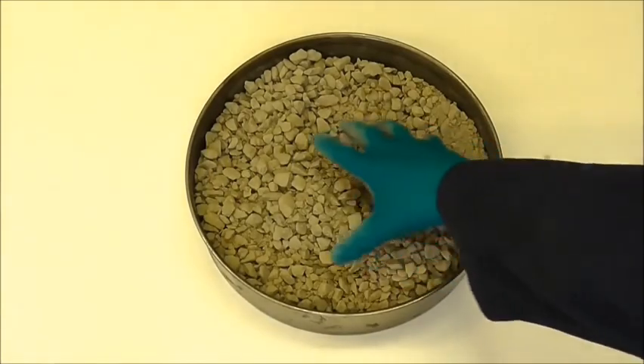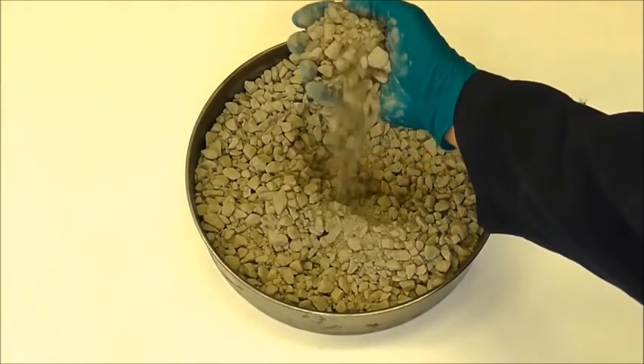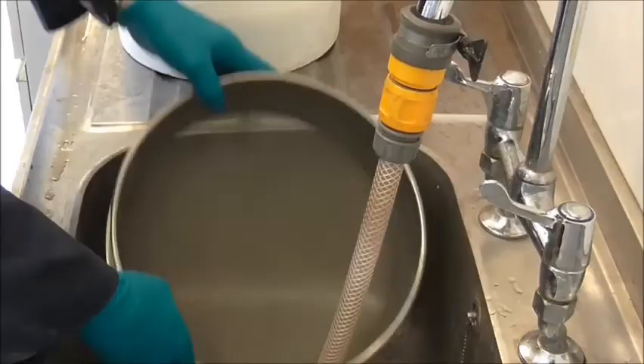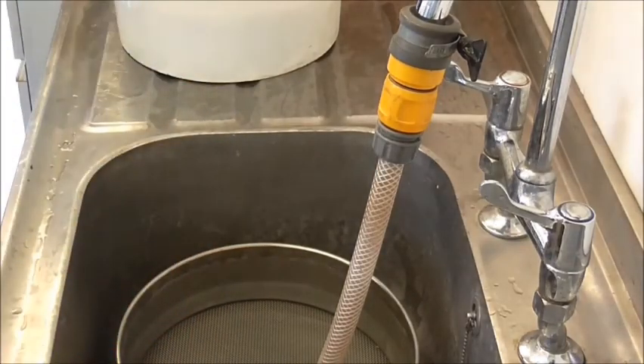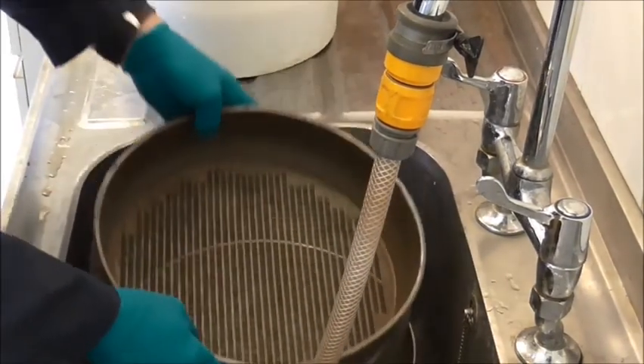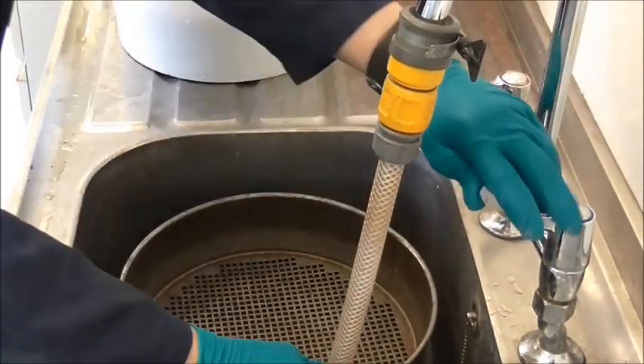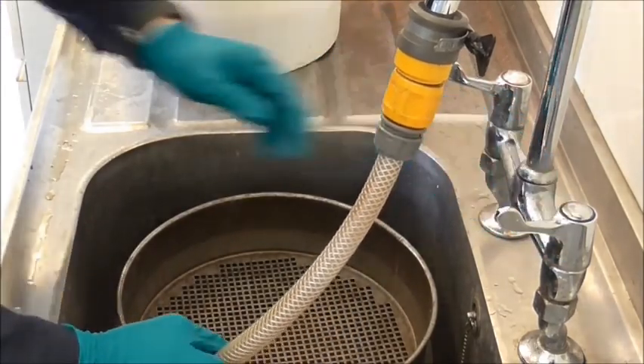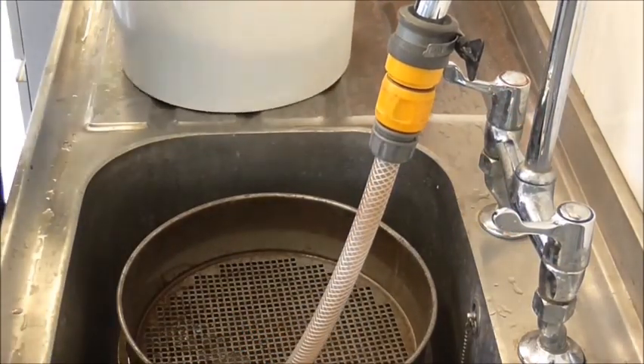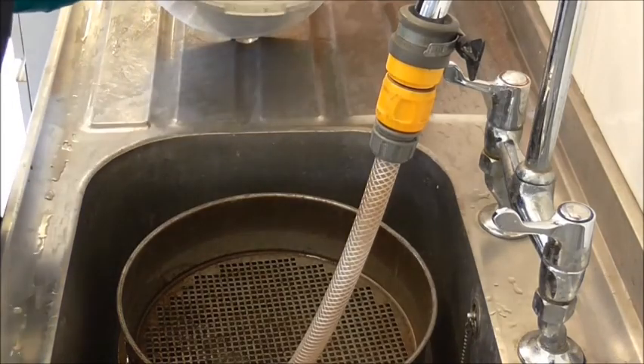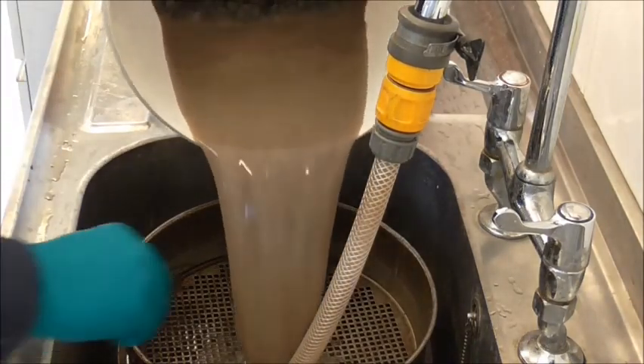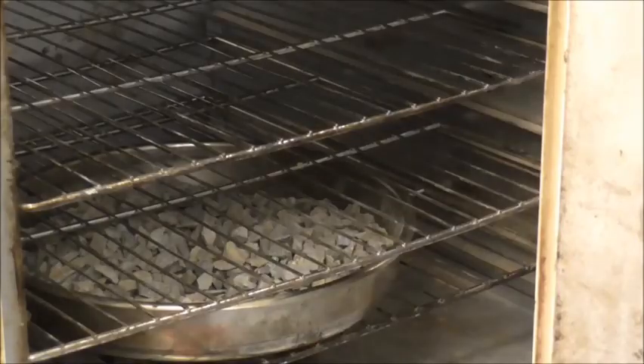The fragmented material is then taken from the tray and washed over a 1.6mm sieve. It's a good idea to protect the 1.6 by using a coarser guard sieve. This sieving operation is done in several stages to avoid overloading. The retained aggregate is then dried to constant mass, allowed to cool, then weighed.